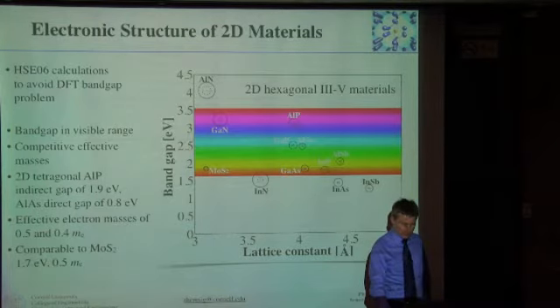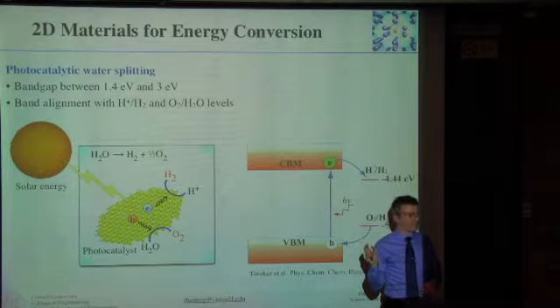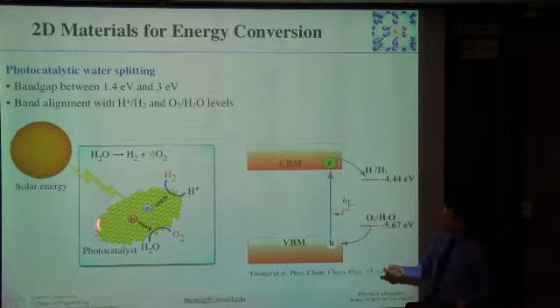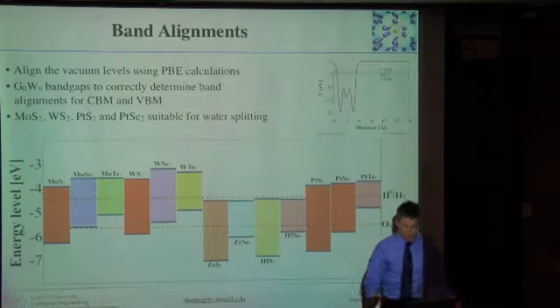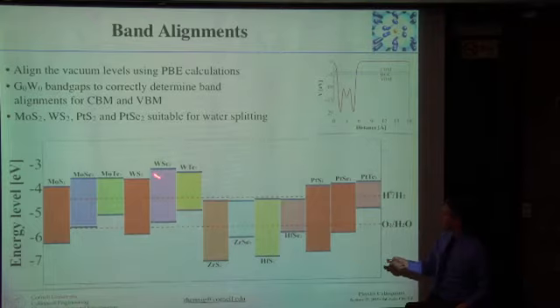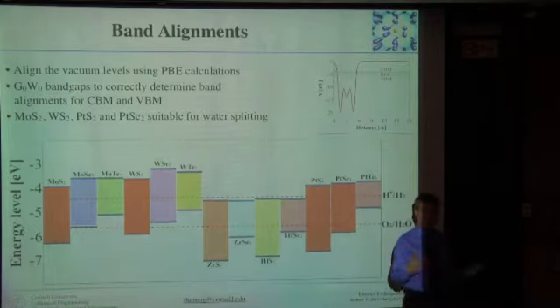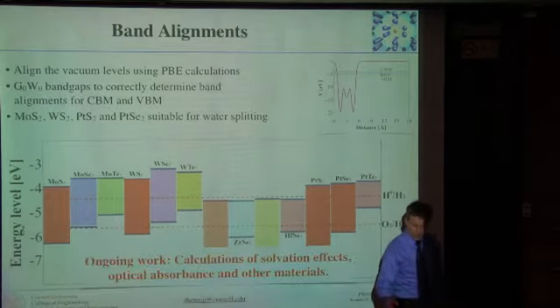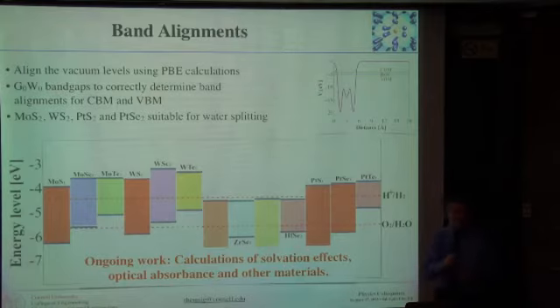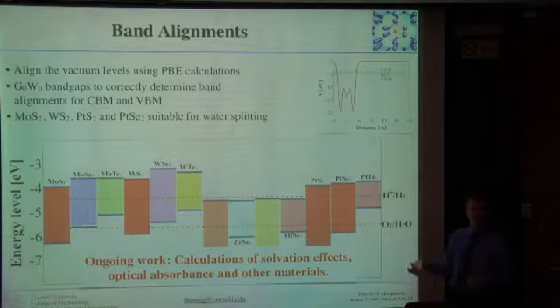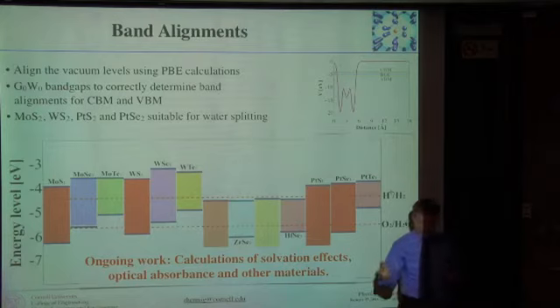With that, I'm actually going to stop. I'm not going to tell you about that we also investigate some of those materials for photocatalytic water splitting to figure out can you use sunlight to split water. I'm going to just show you there's a summary slide that we do indeed find 4 materials which are having the right band alignments with the splitting levels for hydrogen and oxygen evolution of water. And we're currently investigating for these materials what happens if you actually put water into the calculation directly. Remember I told you earlier on that we have a method which describes the solvation, water present in the system, how it's affecting the electronic structure and the stability. That's what's ongoing. This data is only 2 weeks old, so I'm just going to share that with you because we are excited about that.